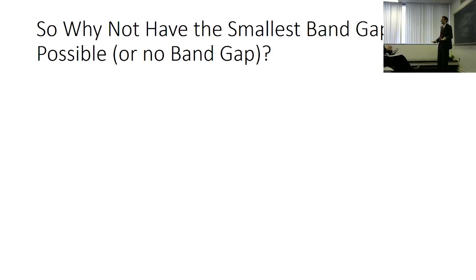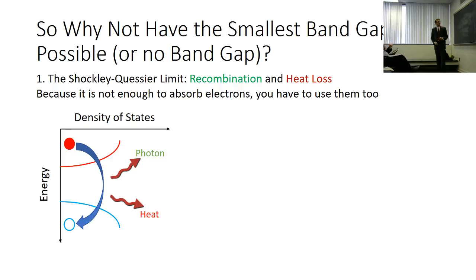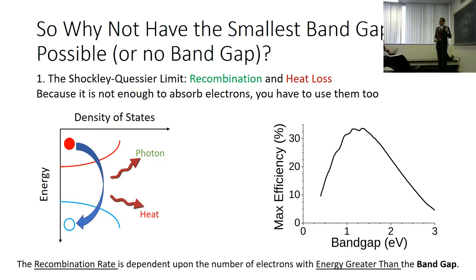Because absorption is not the entire story. You also have to consider recombination. When you promote your electron to the conduction band using a photon, it doesn't have to do what you want it to do. It can drop back down, emitting some energy in the form of a photon, some light, or it can emit heat, which is not useful for your system. It turns out that this rate of recombination, the rate of dropping back down, is dependent on the band gap. If the energy of your photon is much greater than the band gap, it drops back down really quickly.